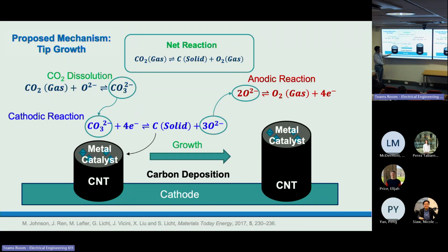So the metal catalyst will facilitate the nucleation of the carbon nanotubes and stay on the tip of the carbon nanotubes. So the carbon nanotubes keep growing from the tip, along with the metal catalyst. And also the oxygen ion will be oxidized to oxygen gas on the anode.